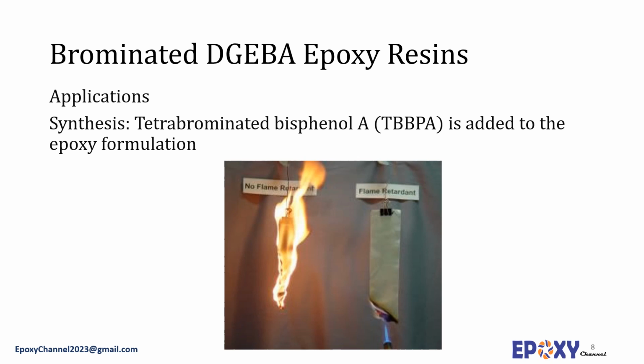Tetrabromobisphenol A is the largest flame retardant in terms of commercial use at present. It is used in an estimated 95% of all flame retardant printed wiring boards, and it is used in many flame retardant surface-mounted adhesives. It is manufactured by several producers, and it is priced as a commodity product. The brominated resins are available primarily as semi-solid or solid in solvent solutions. They have properties similar to those of other diglycidyl ether bisphenol A epoxies, except that the high bromine content, 18 to 21% in the finished resins, provides outstanding flame ignition resistance.